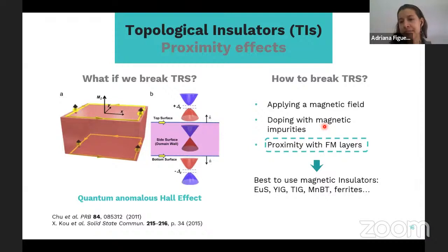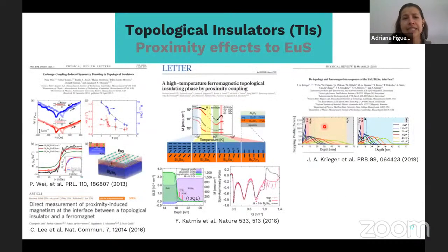So we also explored the use of magnetic insulators to introduce magnetic order in the TI. And this has been studied since the advent of these TIs. Even since 2013, it has been investigated that topological insulators interfaced with magnetic insulators can have very strong magnetic proximity effects at these interfaces. And there have been lots of studies, not only experimentally but also theoretically, where novel phenomena at those interfaces have been explored, and of course you want to exploit those observed properties.